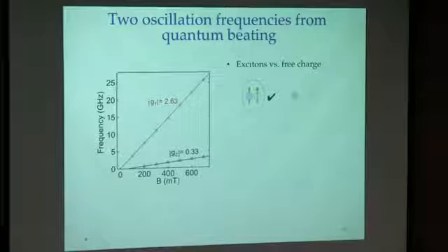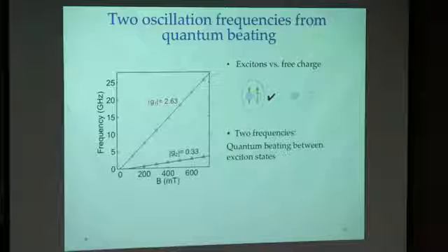Luckily, we have that experimental determination of the exciton binding energy, so we can pretty much say that at low temperature, the photoexcited species are dominantly excitons. So we assume that's the right picture. They are excitons. Electron and hole have some Coulomb interaction and spin exchange interaction. Then the two frequencies must be from quantum beating of the exciton states, and we should describe everything in terms of the exciton picture.